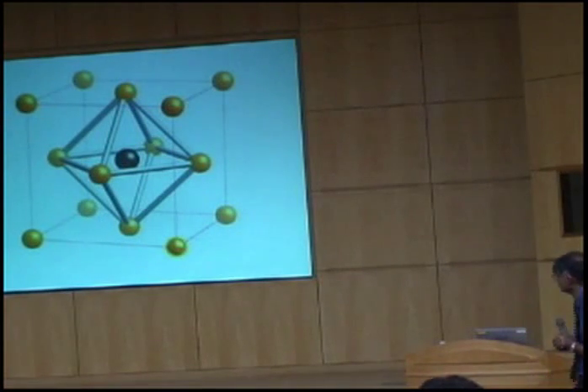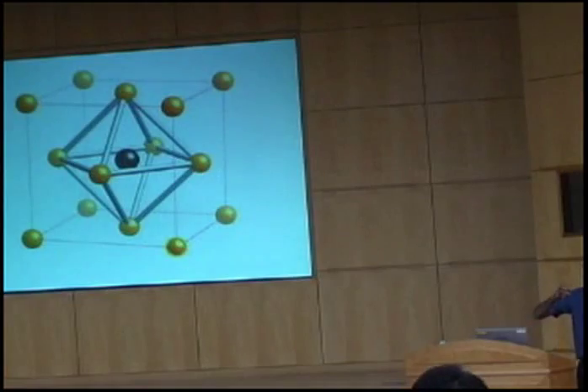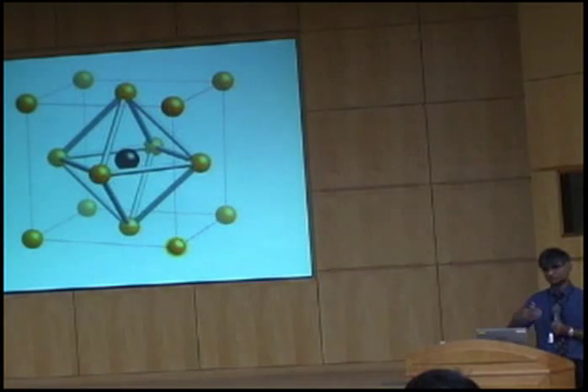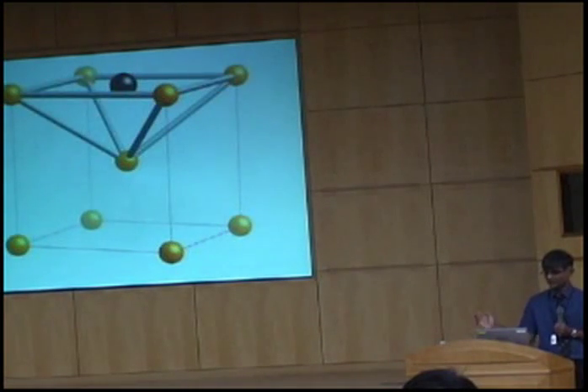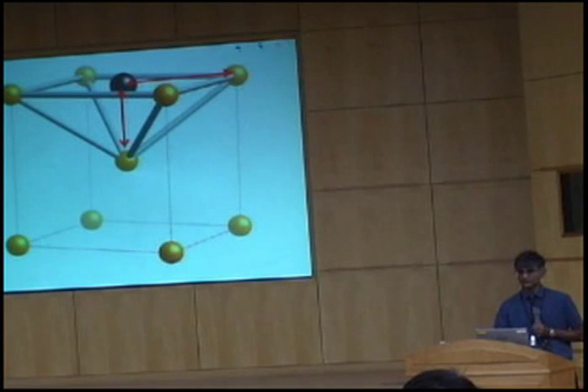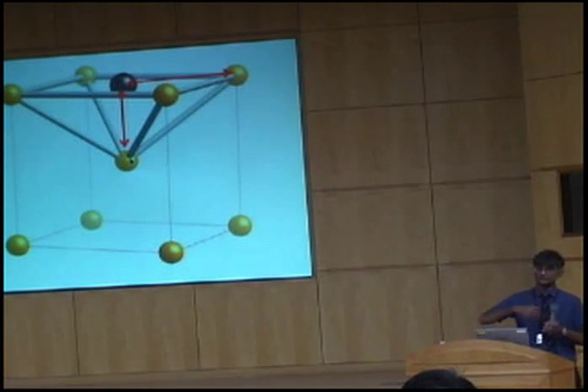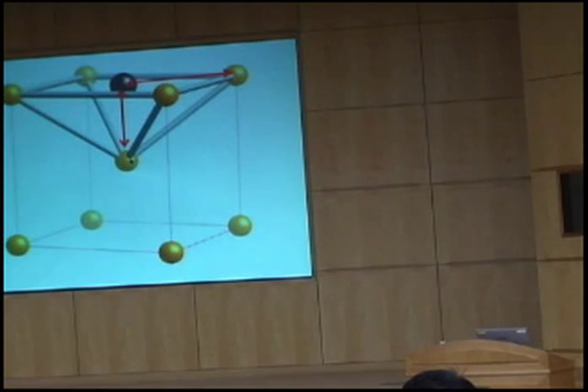Doesn't strengthen austenite very much because a hydrostatic expansion can only interact with the dilatational strain of a dislocation, which is very small. Okay. The major strain due to a dislocation is shear, and the shear can't interact with a volume change. Whereas if you look at ferrite, the carbon atom has different distances here and here, so it's a tetragonal strain. And that tetragonal strain can interact with the shear components of a dislocation. So it's a very powerful hardening mechanism. So it isn't true that carbon always hardens steel very much. It hardens ferrite very much.